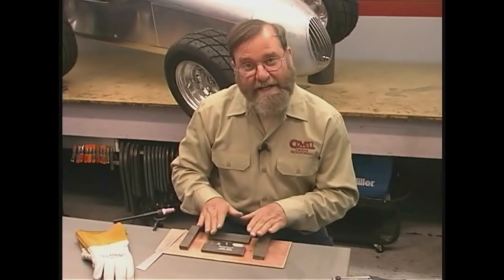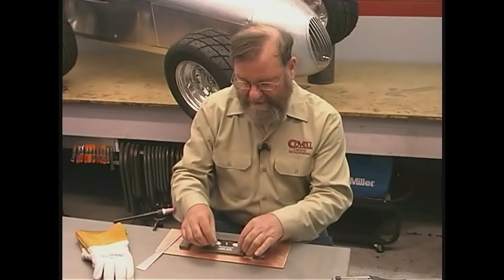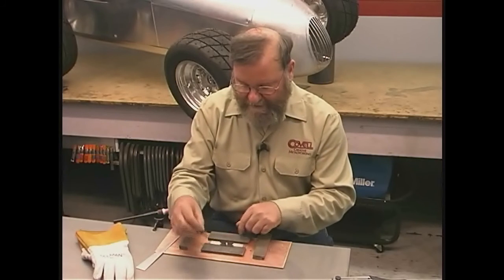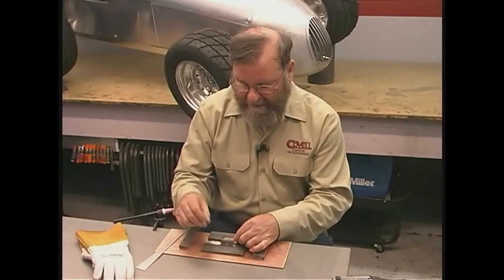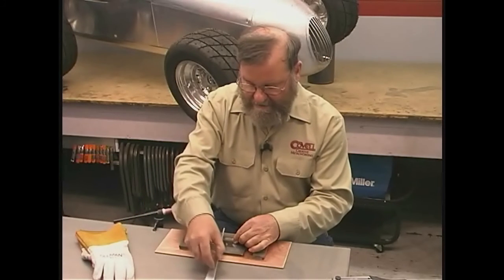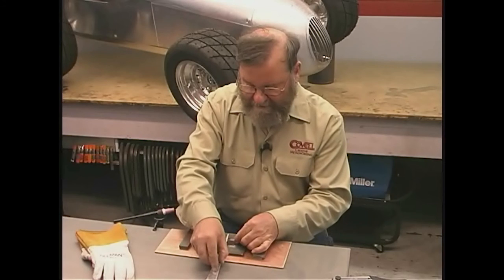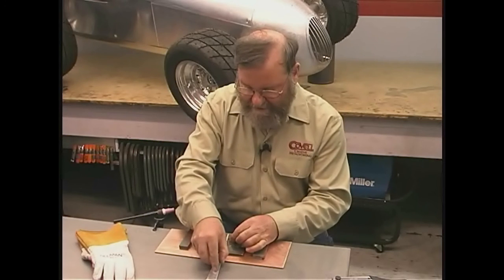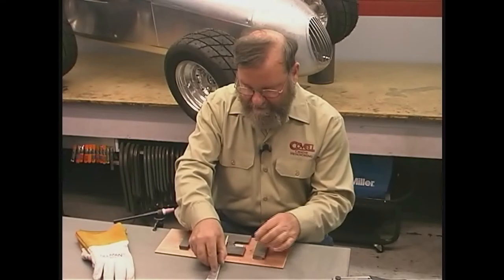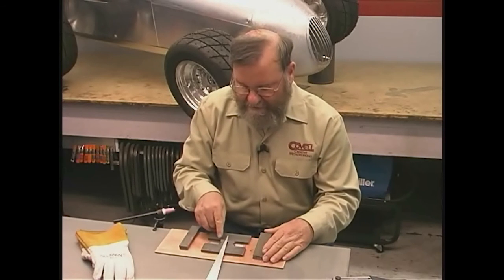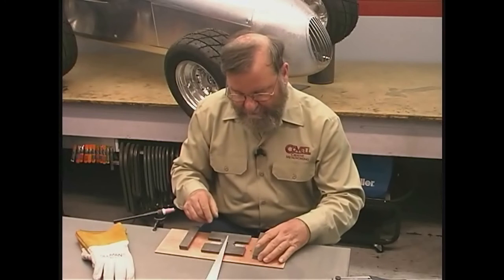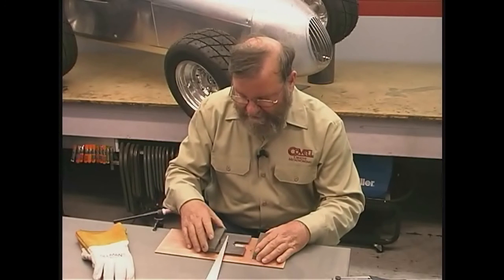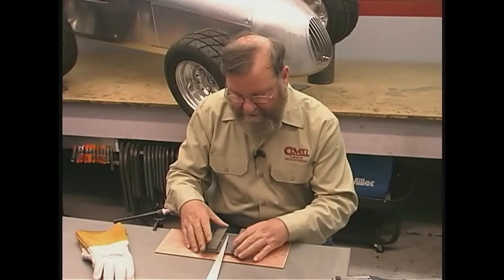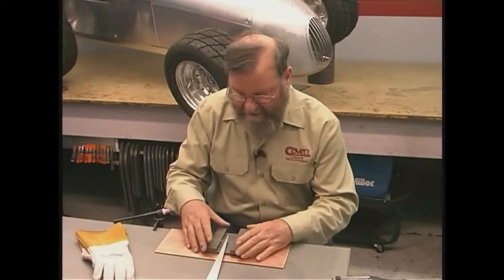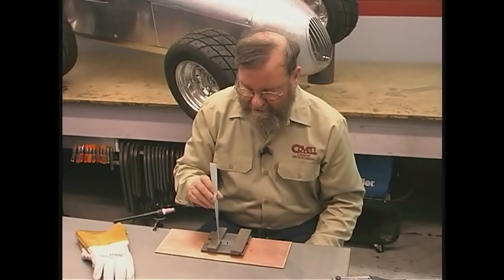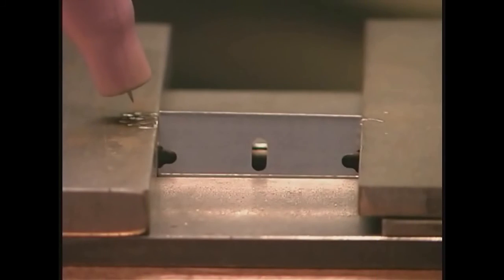So it took a little figuring out for me to perfect the setup for this. What I've done is to put a couple of plates on my table that the back of the razor blades can rest against, and then I just use this plate to angle the tips together until they touch. That's the tricky part. And then it's really hard to start an arc on that narrow little edge. So what I've done is to put a block of metal right alongside the razor blades at both the beginning edge and the back edge, and that gives me a place to start the arc and end the arc. Here we go.